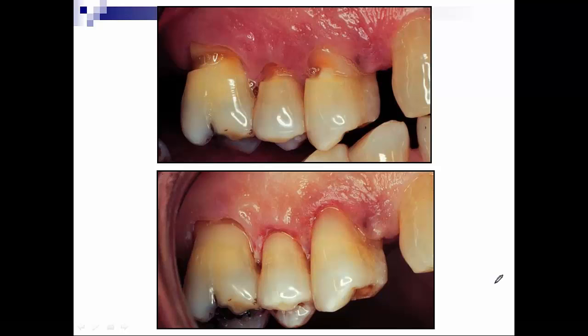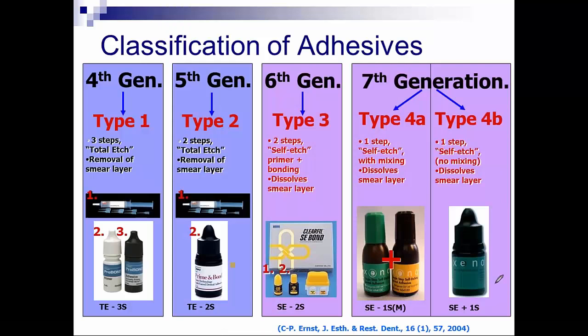Now, if we look at the traditional adhesive systems, 5 years of service with these non-retentive cavities, modern adhesive systems, the traditional etch and rinse or total etch adhesive systems, generate 95% retention rate after 5 years across a number of adhesive agents for these kinds of cavities. So when we talk about newer systems, we have a very high benchmark level.